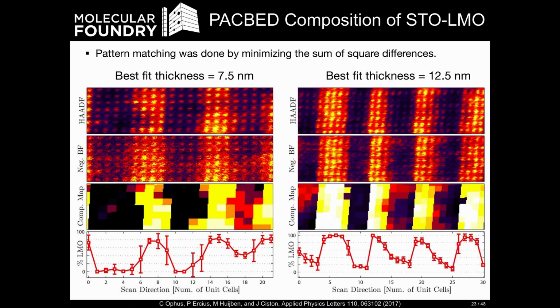In another data set, for example very slightly thicker, a little bit further from the edge of this foil, we get essentially the same thing. This is actually very interesting because this is not a spectroscopic measurement. All we're using is the intensity resolved over the momentum vectors in the PACBED images, and we can pull out very, very subtle differences in these scattering signals, including composition here. And it is very subtle.